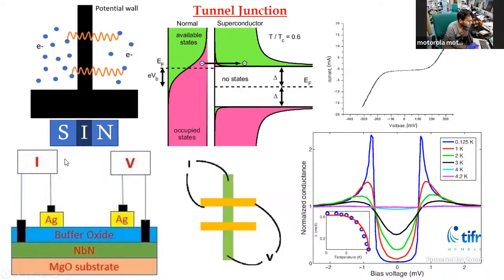For that, we can develop tunnel junctions. Here we are using NbN, then we develop an oxide barrier on it, and then we deposit Ag with this geometry. The green strip lines are our NbN, and the yellow strip lines are our Ag, the silver. By forming this kind of junction, we can visualize tunneling. As I showed you, this is a superconductor density of states, and this is a normal metal, and in between there is an insulator that works as a vacuum. If we are going to do STM, that will be described later. In a normal metal, electrons can go from this region to this region, but electrons can't go to this region.